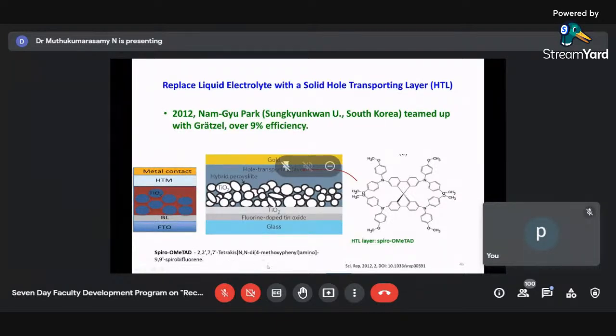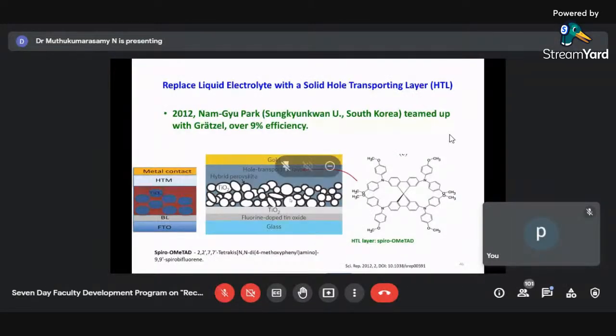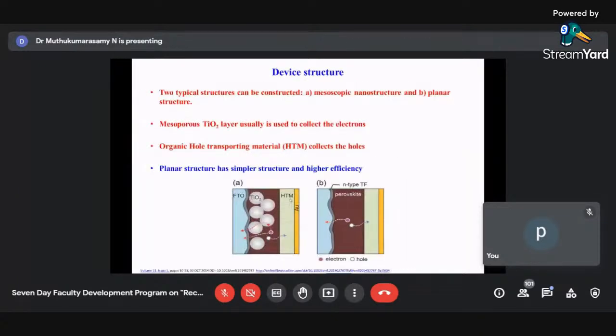It is tetrakis methoxyphenyl amino Spiro bifluorine. People who are working in chemistry may know better about this organic type of material, and he used that, and he got an efficiency of 9%. So this was the first perovskite type of solar cell where the titanium dioxide material was mixed with perovskite and used as a light absorbing material, and the liquid electrolyte was replaced by a solid hole transporting material, an organic material, Spiro, and they got an efficiency of 9%, but there were stability issues associated with it.